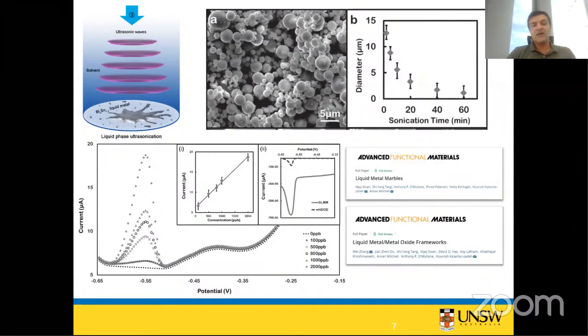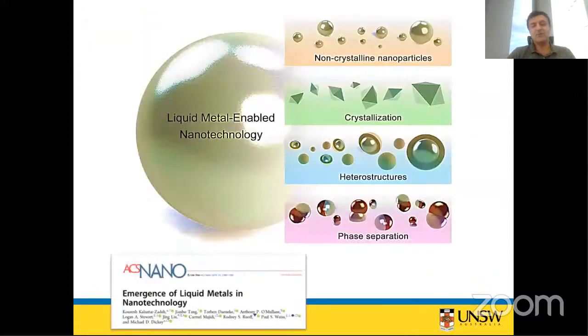So we can then have these very high surface-to-volume ratio droplets that you make films from, and you can use them for different applications. For instance, here we use them for making functional materials for sensing. This is stripping voltammetry. You apply a voltage, for instance, when you want to detect cadmium or lead in the water. You apply voltage, these cadmium and lead ions go and amalgamate into gallium, then you reverse the voltage, they come out, you measure the current, and the current is proportional to the concentration of heavy metal ions in the environment.